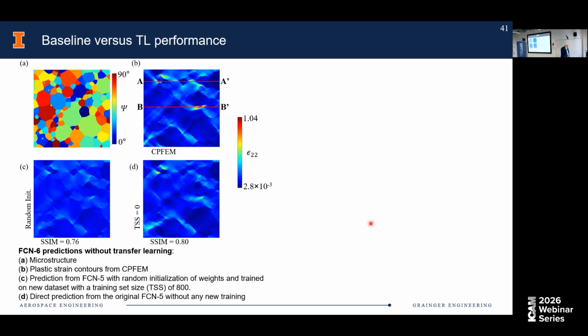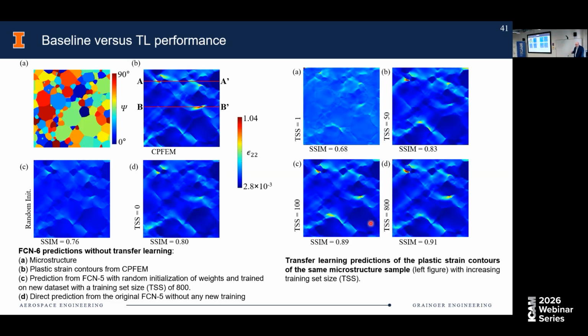If we do transfer learning with one sample of the new material, it's not very good. But that's because it's way overtrained. But if we do as little as 50, and then this goes up to 100 and 800, we actually get very good results. So transfer learning, at least within groups of the same material, seems to be possible to work pretty well. So for me, this is kind of an eye towards, well, if we can actually train something numerically and then sort of adjust for that with a small number, 50 experiments, for example, is doable, right? 50, maybe 100. 9,000, maybe not so much, right? So this sort of transfer learning seems to be a good scheme to be able to move in that particular direction.